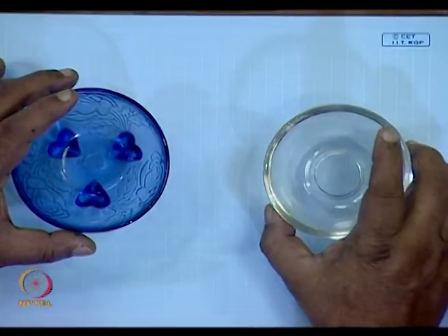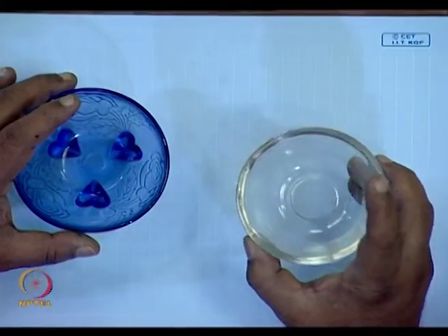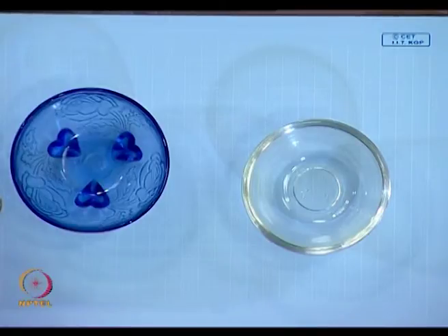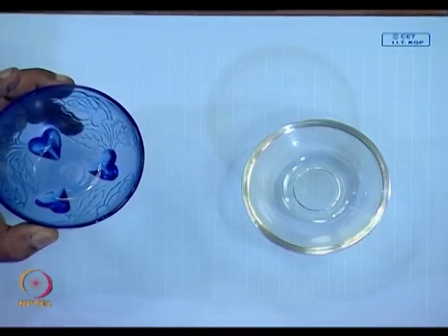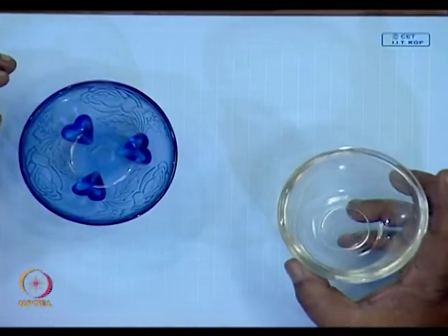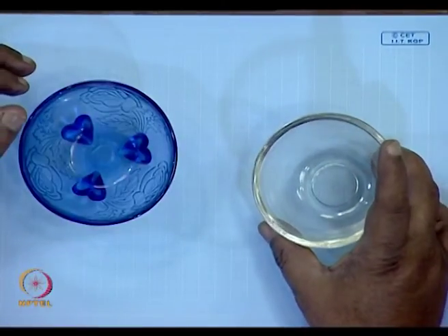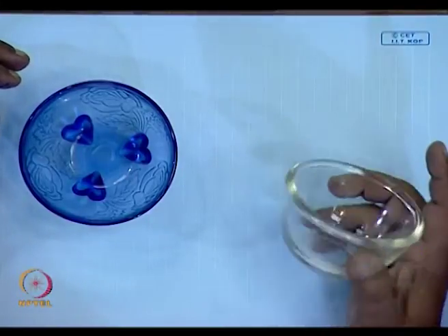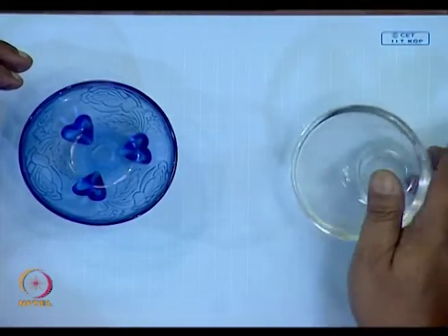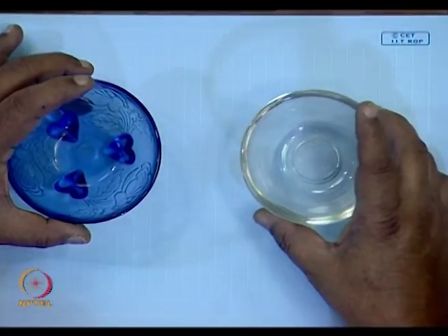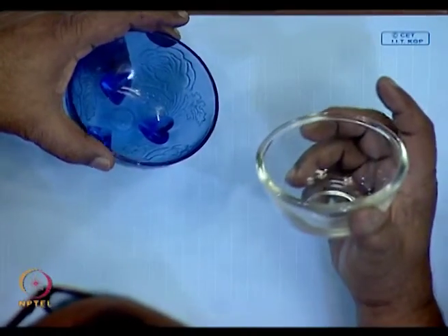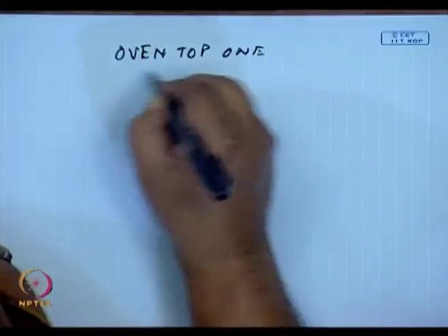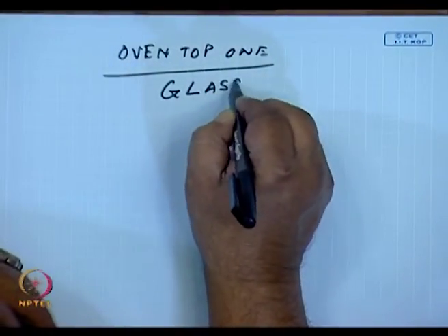This one, I can heat on a gas flame, cook in it, and then immediately put it in cold water. It won't crack. I try to heat this in a microwave oven, this will crack. This one will not crack. This is really called an oven top cookware, in which I can cook even on top of a gas stove and then place it on a cold plate or even water. So there is a substantial difference between this and this. The difference is that the oven top one is a glass ceramic.